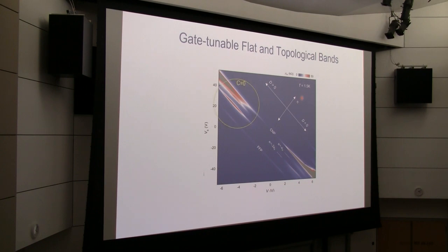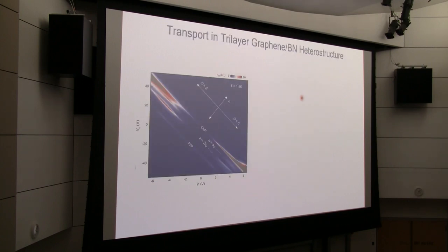According to the theory, with positive electric field, we'll have a flat band, but it is more like a common flat band, a trivial flat band. And on the other side, we'll have a topological flat band. So we can see in this phase diagram what happens. Let's first look at the transport on the trivial flat band side. If we do a line cut at zero vertical electric field but vary the doping, this is what the transport looks like. You see some resistance peaks, and one of the peaks corresponds to the charge neutral point in the system. The other peak corresponds to completely filling the band, which corresponds to 4 holes per lattice site, because in graphene you have both spin and valley degrees of freedom.